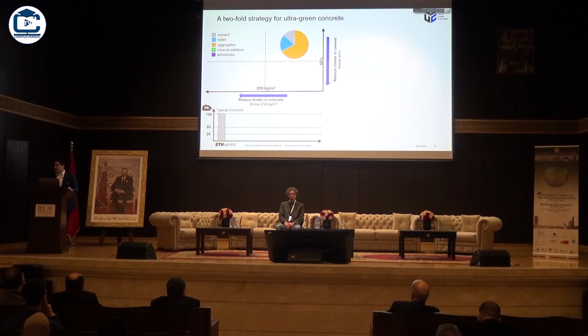So this is the benchmark that we are using, and we normalize that one to 100 to make it easier to compare. So that concrete will have a composition more or less like the pie chart that you see here. And with things like LC3, we already go a long way because we can replace half of that cement with a combination of calcined clay and limestone, and we can reduce our CO2 footprint by about 30 to 40%, which is what we see here.